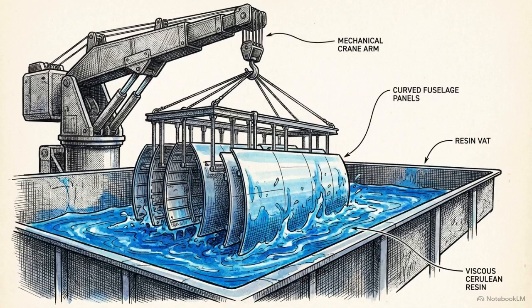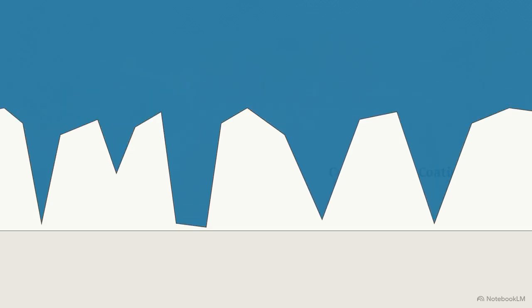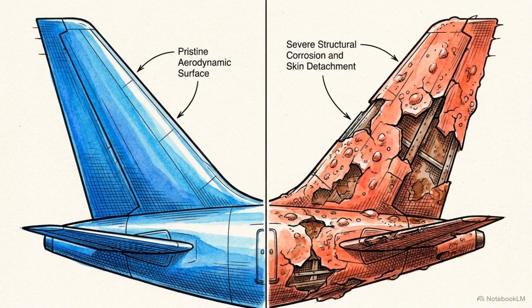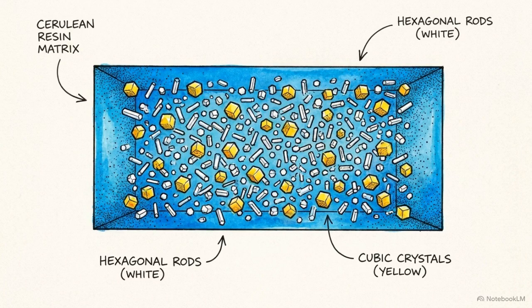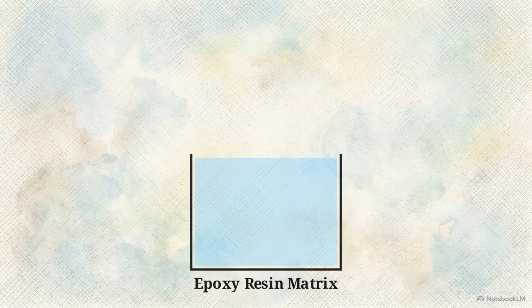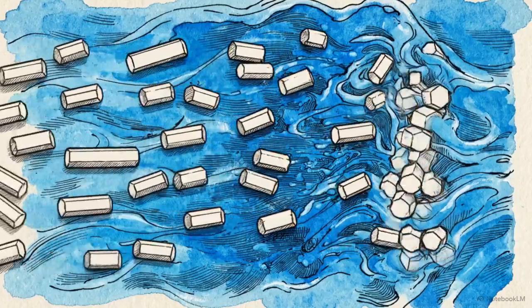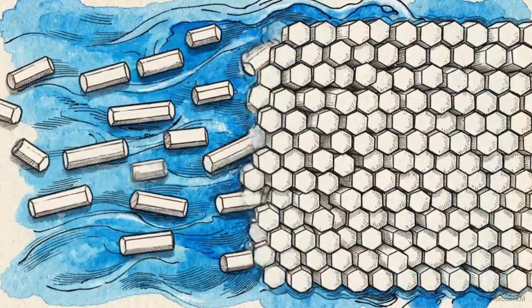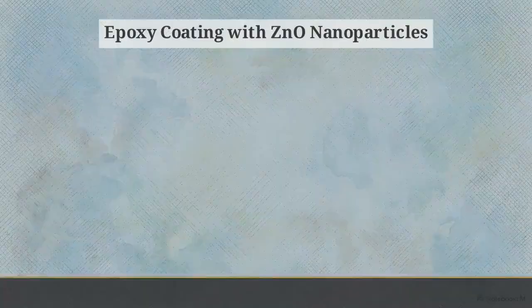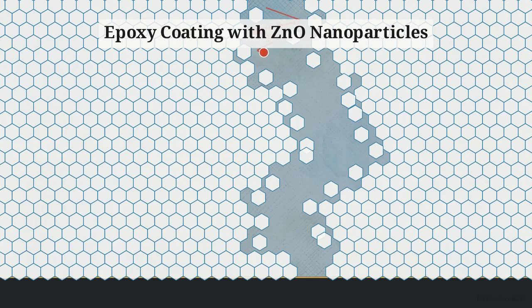A chemical-resistant epoxy phenol novolac resin is applied via dip coating. The liquid epoxy flows into the craters and mud cracks, structurally interlocking with the ceramic skeleton before solidifying into a tight bond. The epoxy fills the macroporosity, but a bare polymer remains too permeable at the molecular level to survive a 30-year service life on its own. The final layer of the architecture embeds a 3% weight dispersion of ceramic nanoparticles directly into the epoxy matrix. To optimize the nanocomposite, the formulation uses 1 part zinc oxide to 2 parts cerium oxide. The zinc oxide nanoparticles serve to densify the polymer matrix, acting as highly dispersed physical obstacles against invading elements. This creates a tortuous path, preventing electrolytes from traveling in a straight line toward the metal.